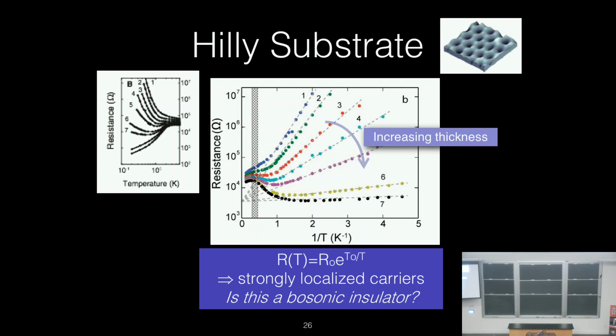And what Stu found, who was the student that did this, his thin film, he measured the resistance as a function of temperature. It rose exponentially as he lowered the temperature. He made it thicker. The rate at which it rose exponentially dropped. And then it went through the superconductor to insulator transition. But what he found in this region was that the resistance grew exponentially as he lowered the temperature. And that's a sign that the carriers, the Cooper pairs, are actually stuck on grains, and they have to hop over a barrier to get around. Is this a bosonic insulator?